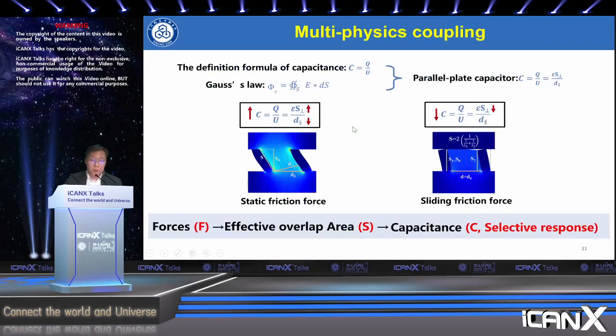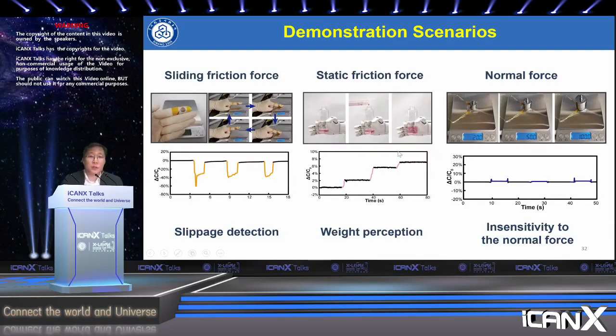And how does the deformation affect the capacitance of the sensors? We analyzed the coupling between the solid mechanics and electrostatics. For the static friction force, the effective overlapping area increased during loading of the static friction force, causing an increased capacitance. Conversely, the capacitance decreased under the sliding mode due to the decrease of the effective overlapping area. And then we did some demonstrations. We put this friction force sensor on our gloves. When we slide over the weight, we can see in real time that the capacitance decreases. It's good for slippage detection.